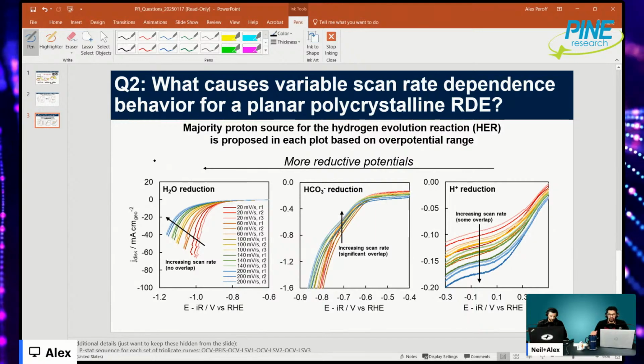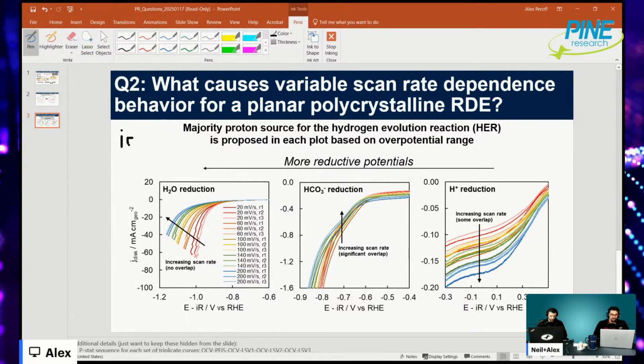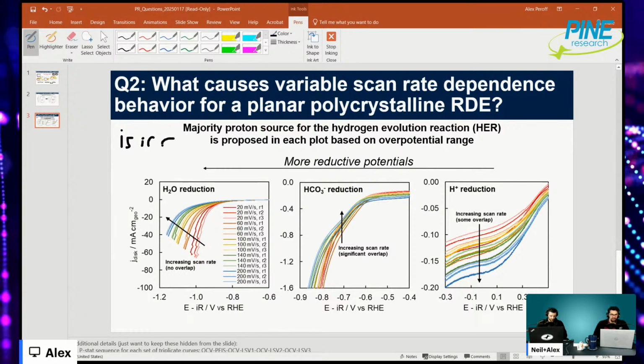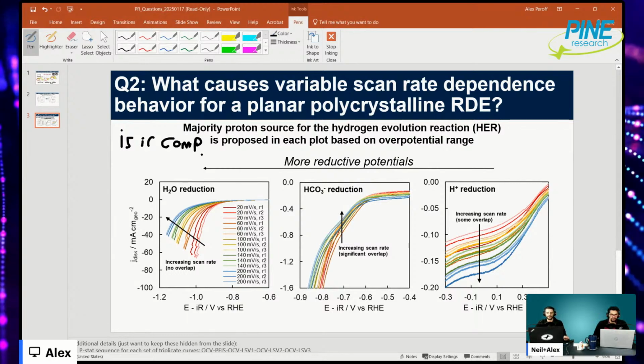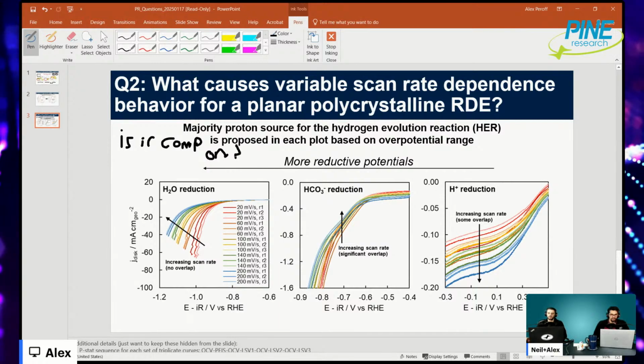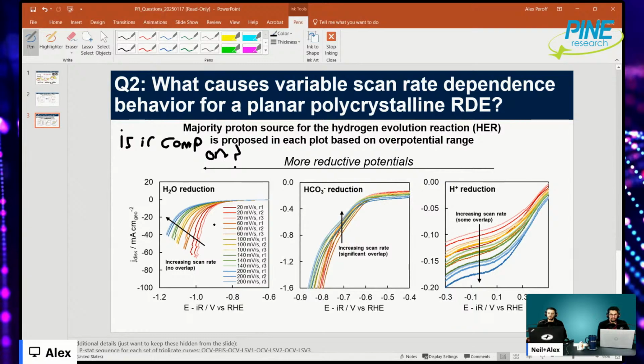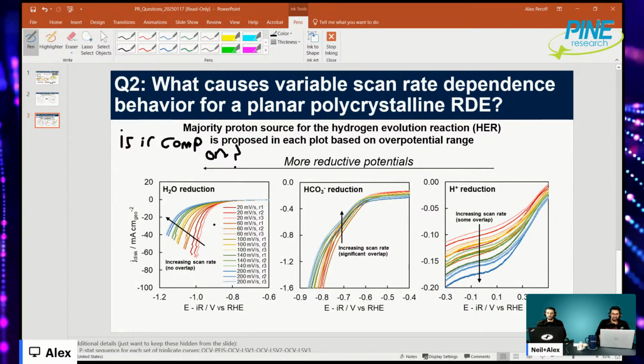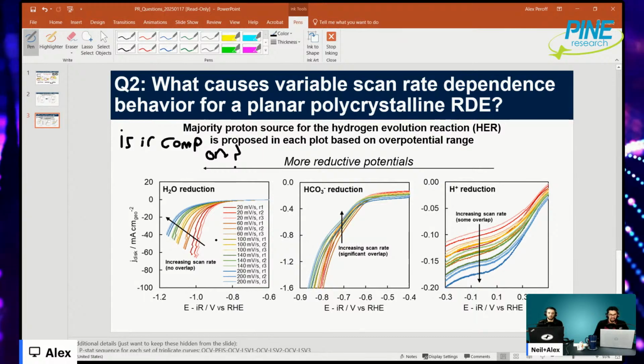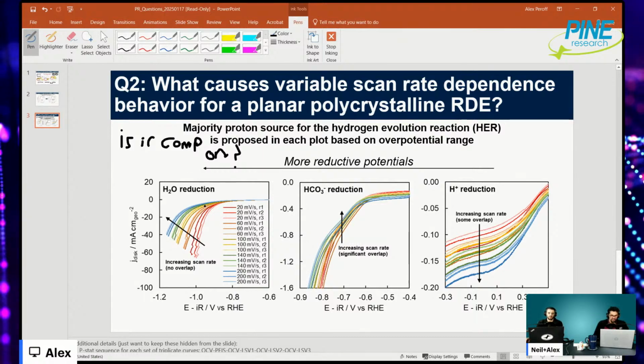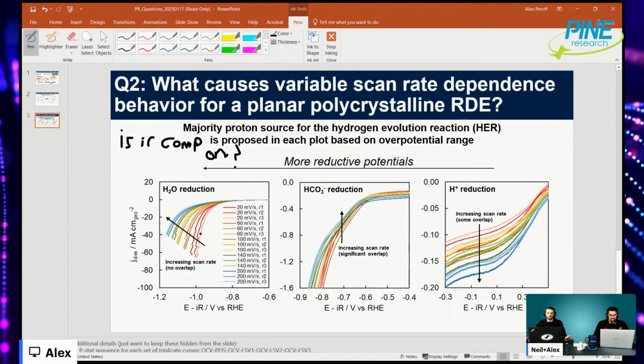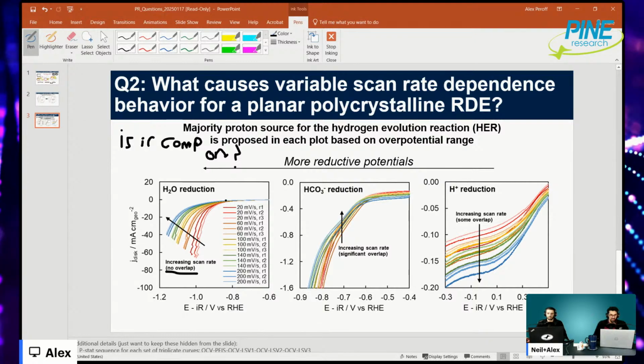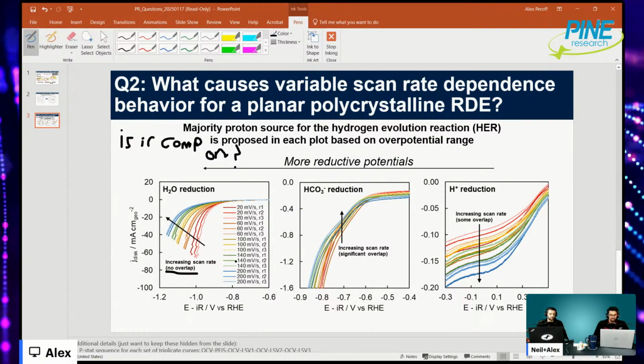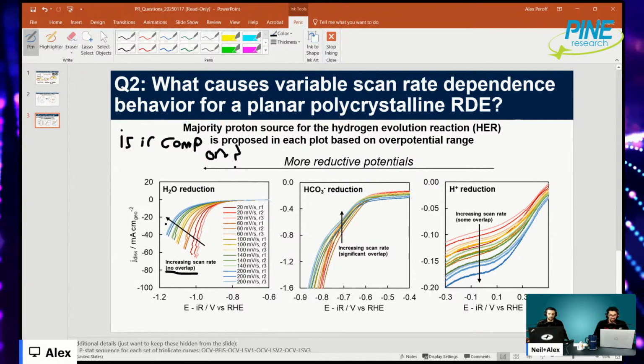the potential, right? So one question is, is IR comp on for these experiments? I'm not really so sure, because some of the data actually will make a lot of sense if IR compensation is not on. Because one thing that's particularly interesting about this water reduction is it's not really so much that there's no overlap. It's more that the onset potential keeps getting higher and higher as you increase the scan rate. That is actually probably the more interesting result about this water reduction.